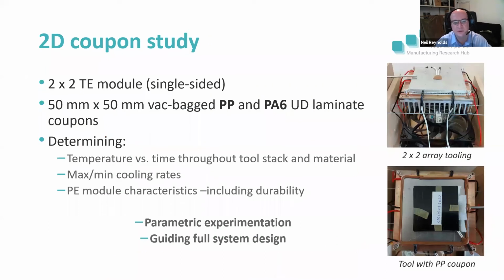So we're now in the middle of the 2D coupon study. You can see the apparatus on the right-hand side. It's a 2x2 array of Peltier modules. We're looking at polypropylene and polyamide 6 UD tape laminates. So they're going in dry, and then we're doing the full consolidation under a vacuum bag. And we're measuring the temperature at the tool and inside the material and establishing key criteria such as maximum and minimum cooling rates and, as discussed, the actual characteristics of the modules themselves. Could you move to the next slide, please?